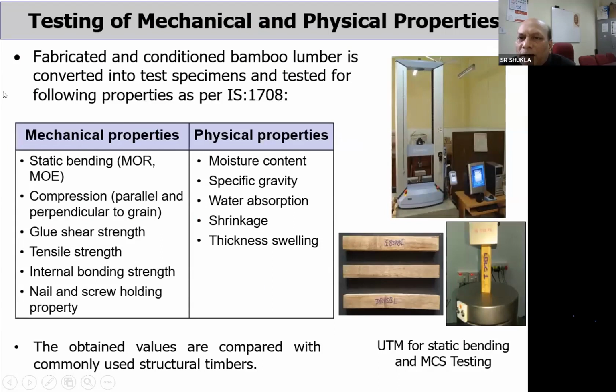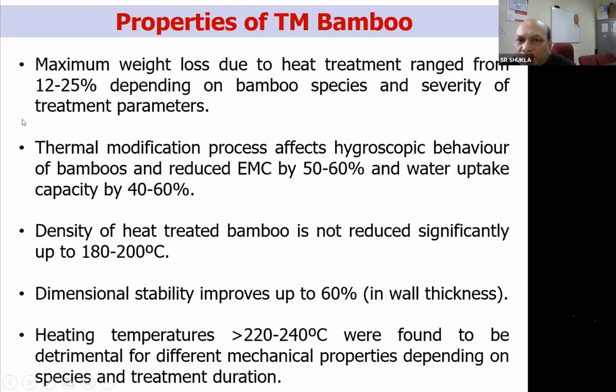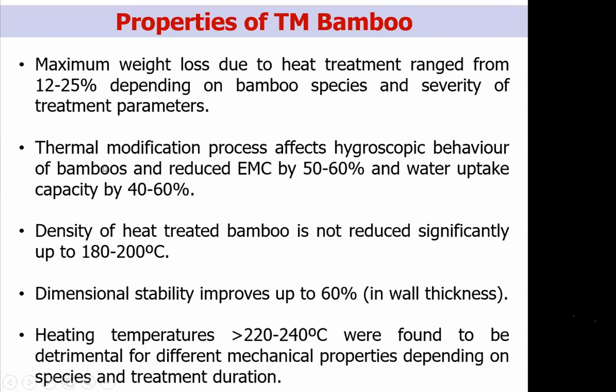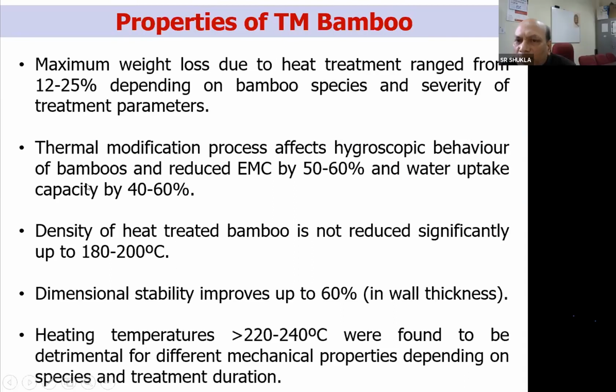Then we have to measure different physical and mechanical properties of the bamboo using the testing facilities available here. And these are some of the properties, like maximum weight loss of the bamboo when it is heat treated ranges from 12% to 25%, because moisture and some of the volatile chemicals will evaporate from the bamboo, and then the weight of the bamboo will be slightly reduced. Then the thermal modification process affects the hygroscopic behavior of the bamboo, and the equilibrium moisture content in the bamboo goes down by 50 to 60%.